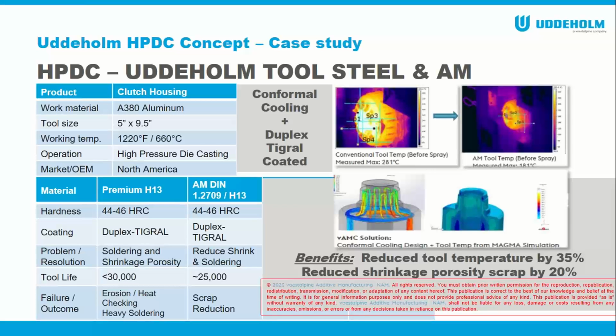With that shrinkage porosity, the scrap was well over 20%. I think at one time it was close to 30. And you can just imagine you have to backfill and remake those castings, and the whole headache all the way down the line. Tool life was respectable, but tool life is irrelevant if you're not making good castings.